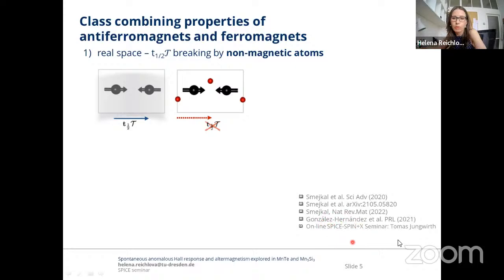So let me just show the simplest cartoon, the simplest core principle of where this additional class of materials comes from. Let's take our simple collinear antiferromagnet, where we have two arrows pointing in the opposite direction. And as I said, when we flip the spin and shift it by half unit cell, we recover the original picture, and therefore we say that the t1/2 T symmetry is preserved.